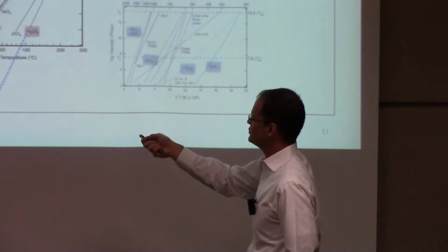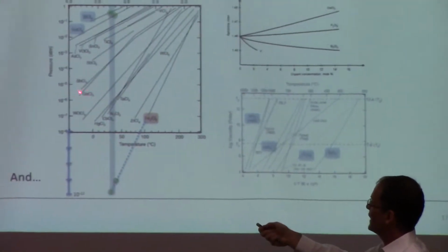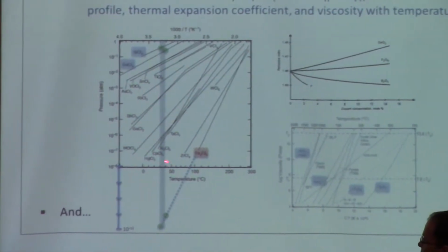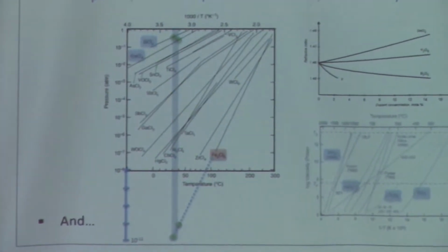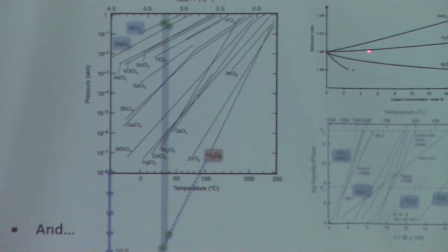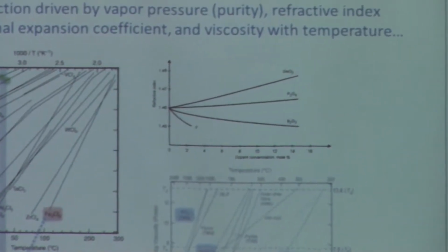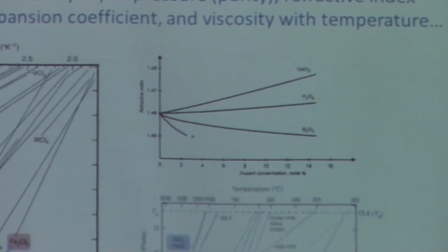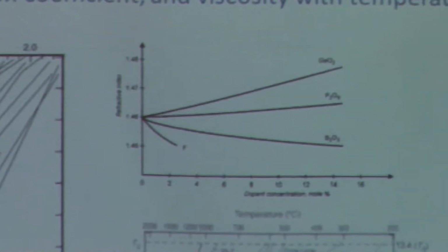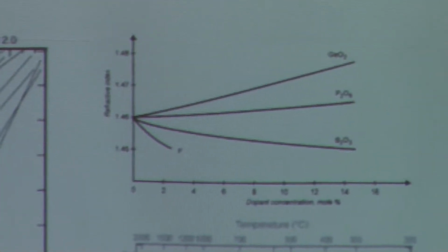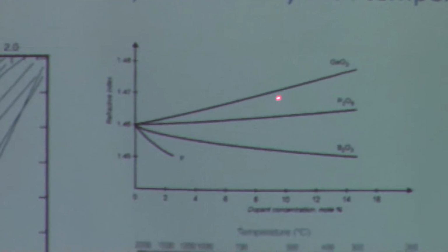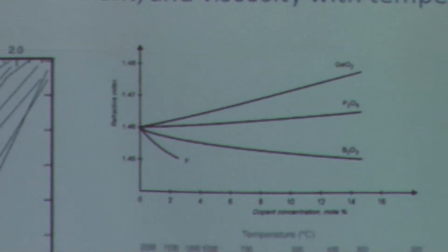However, you have other things that you may want. Aluminum you could want, gallium you may want. So there are these big vapor pressure differences that restrict portions of the periodic table. This is refractive index. It's hard to see. But again, you need to confine the light in the middle of the fiber. That requires you to have a denser, more optically dense core than the cladding that goes around it. Certain things raise the index, certain things lower the index.